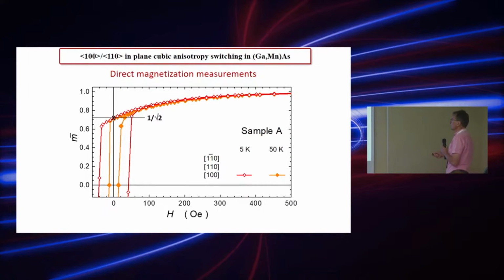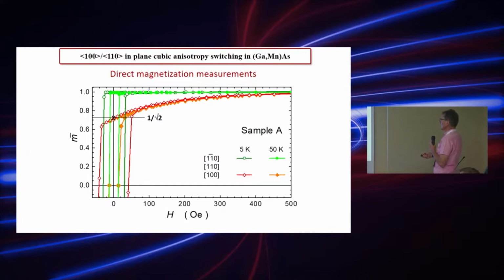So now I'm showing you the results of direct SQUID magnetization measurements. Open points are from 5 Kelvin and full symbols are from 50 Kelvin, and measurement along this 100 orientation, the one which is of prime interest for us, actually shows no difference whatsoever. So the behavior of this magnetization is directly controlled by the uniaxial magnetic anisotropy, and there is very little seen here. So let's go to the 110 orientation, the orientation into which cubic anisotropy switches. But again, there is no difference. Both temperatures, open and closed symbols, show basically no big difference, except for the width of the coercive field, but that is too little to say anything about magnetic anisotropy.